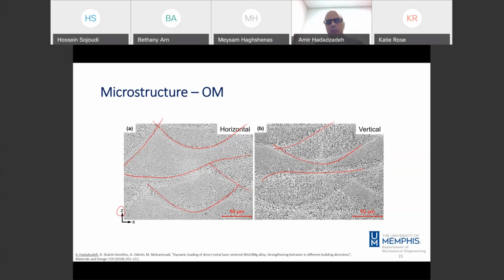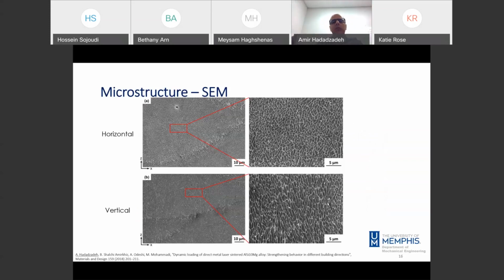And there are some other features which cannot be explored by optical microscopy. So I moved to scanning electron microscopy to see more details of the structure. And here we can see the so-called cell structure of the material. Cell structure is developed because of solidification. We have solidification during the process. We have a liquid material, and that liquid material solidifies once the laser leaves the melt pool. And because of the high cooling rate, the microstructure is very fine. So the cell structure is now revealed here.